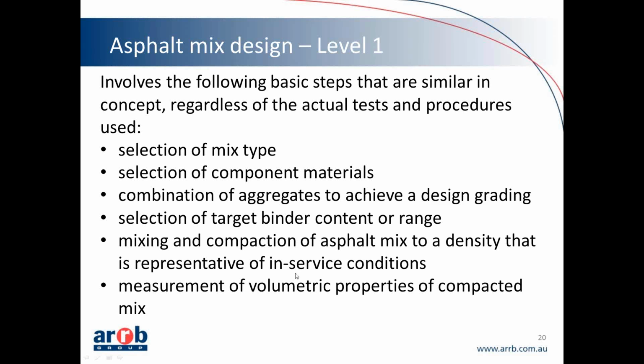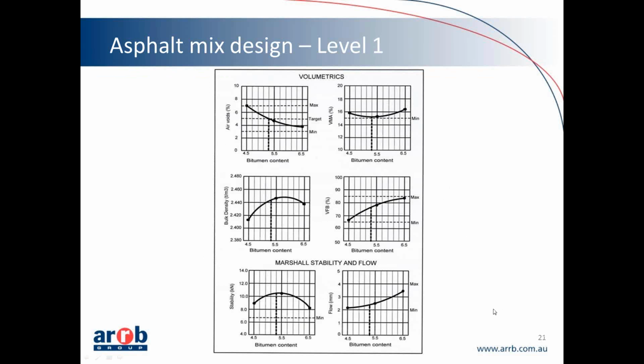Moving to the next slide, that gives you a visual experience of where the volumetric properties such as the bulk density, the VMA, the VFB, and the stability and the flow are visualized as a function of the binder content. The Marshall stability and the flow may also be included in this analysis. It's definitely included in Part 4B, as these properties really form part of the optimization of the volumetric properties. But we need to keep in mind that these two properties are not particularly considered a good performance indicator, and additional level 2 testing may also be undertaken on mixes designed using the Marshall method. But that also relates mainly to heavy-duty mixes.